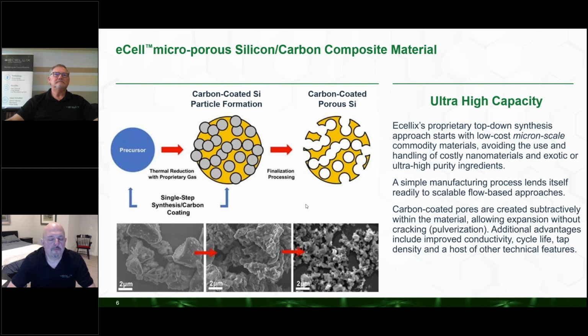Our novel material approaches this in a very clever way. We start off with a very simple metallurgical grade silicon, very inexpensive, very easy to handle. We alloy it with a metal. We then subtract that metal, and what we're left with is something that looks like Swiss cheese. As you can see here in these three photographs, in the left-hand photograph, we're starting off with silicon particles. We alloy it with a metal. In the middle photograph, these are scanning electron micrographs. And in the right side picture, we actually have what's left of our material.